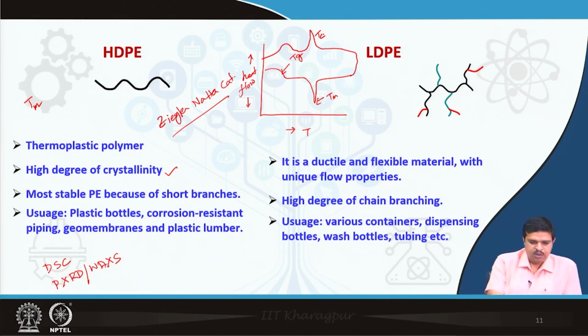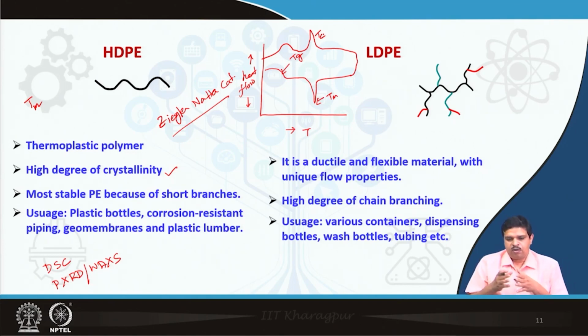Although this polymer crystallinity depends on the thermal history, okay, as I very briefly discussed in the last classes, the polymer properties are a little different from small molecules. So, what happens is, suppose you are synthesizing the polymer, normally we isolate by precipitation. If you do the phase separation very rapidly, then the crystalline polymer can show amorphous nature, and if you heat it, what we generally call annealing, just below the melting temperature and keep it for some time, and then you cool it, you can get the melting temperature if we perform the DSC experiment. So, you have to be careful for that one, okay.